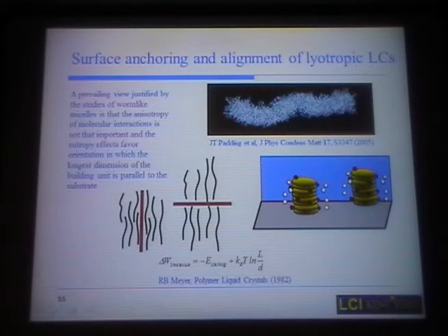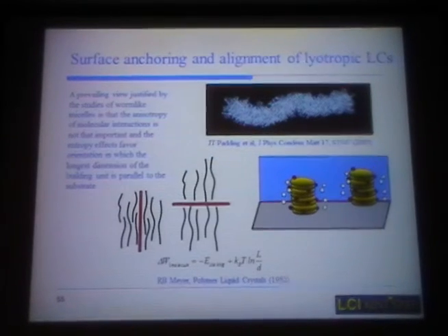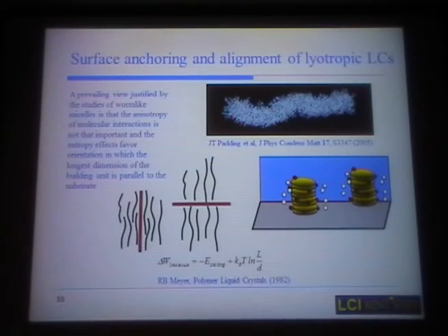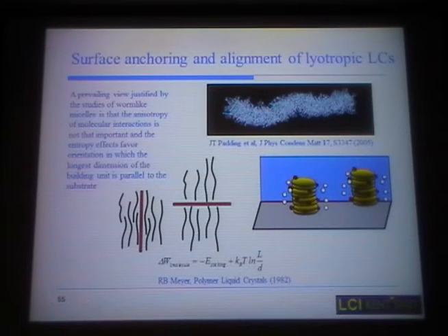The short answer is that you can still find the materials that would provoke the homeotropic alignment. Planar is relatively easy, you just use polymers and rub them. But the homeotropic is really difficult. But if you think about what type of materials you can use, for example, materials with a polyaromatic structure as the aligning substrate, then you can achieve both planar and homeotropic alignment.